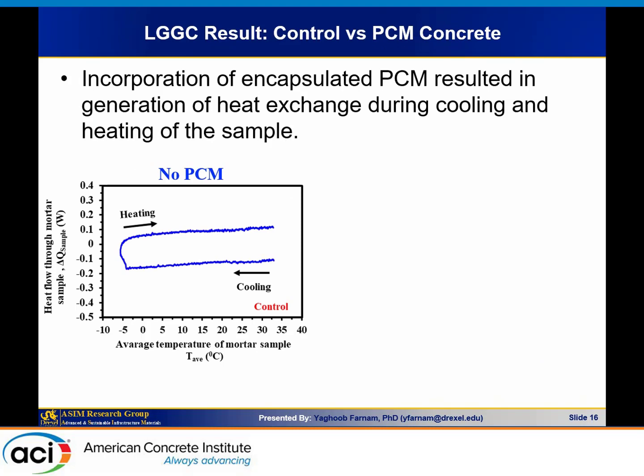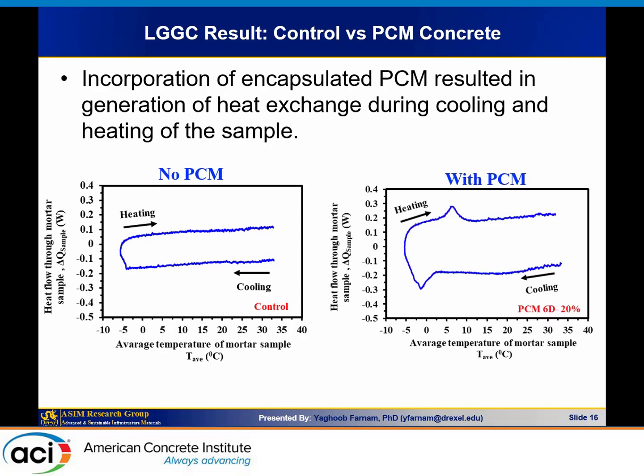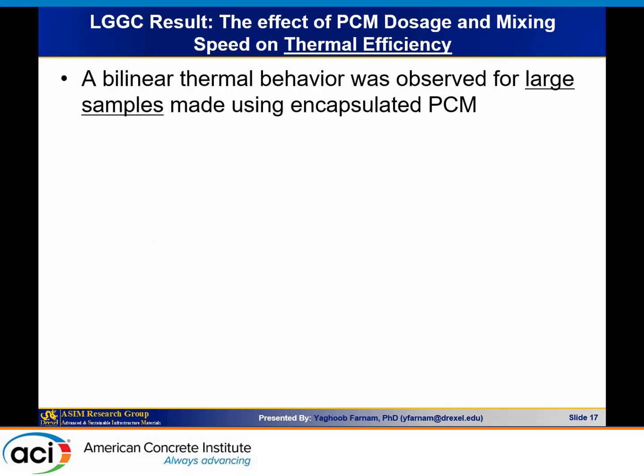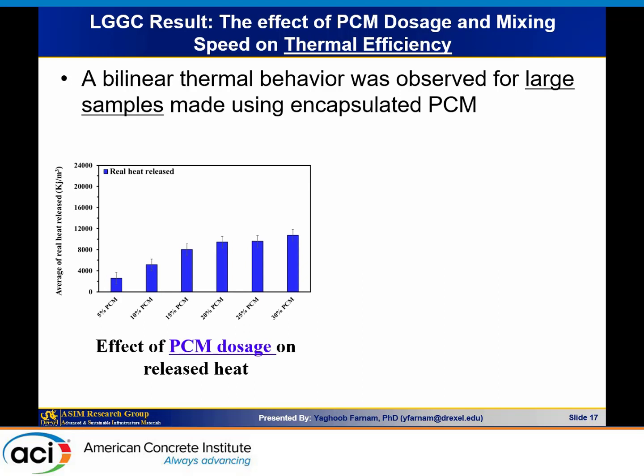So if you look at that, no PCM, no spike, no peak there. And this is something expected. And again, with PCM, as we cool down the sample, we get heat release. And as we increase the temperature, we go back to the heating cycle, then you get storage there. So again, we could do the integration of the area of that peak. And this is the result that we get from LGGC, large scale. So something interesting we observed when we scaled up our sample. At the beginning, when the amount of PCM is lower, we do get linear behavior. And again, when we increase the dosage and we are over 20%, then the slope varies. So some type of bilinear effect. So we want to be very careful.